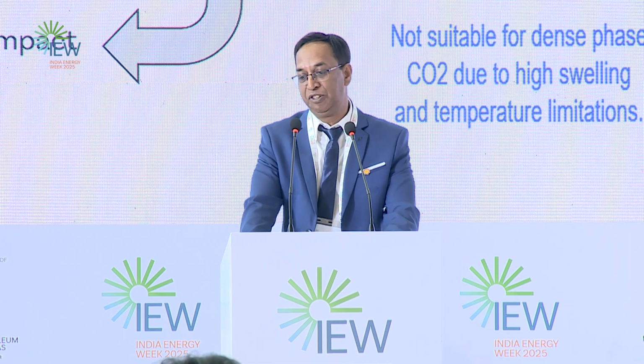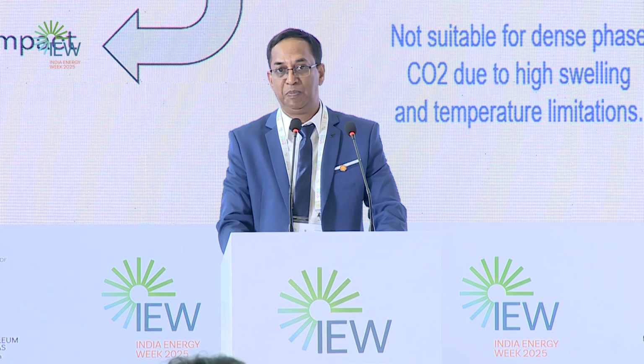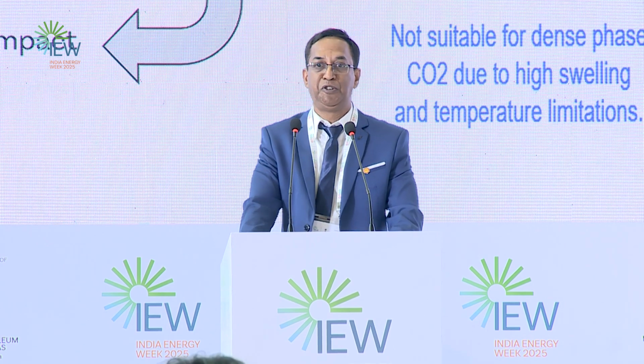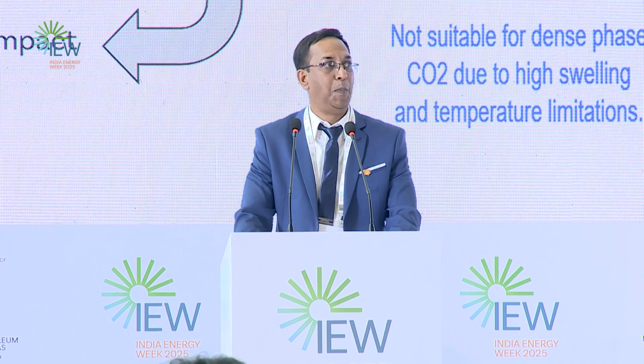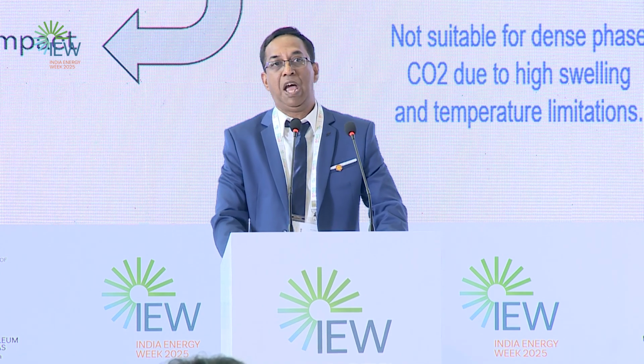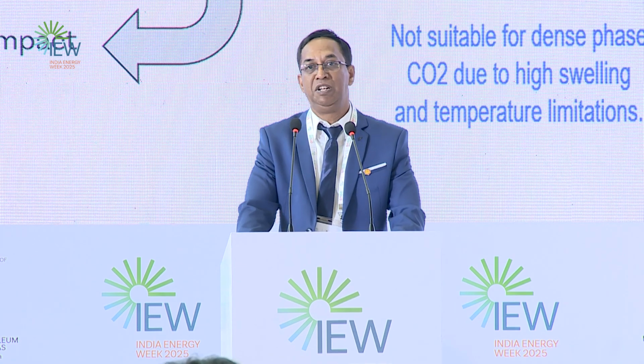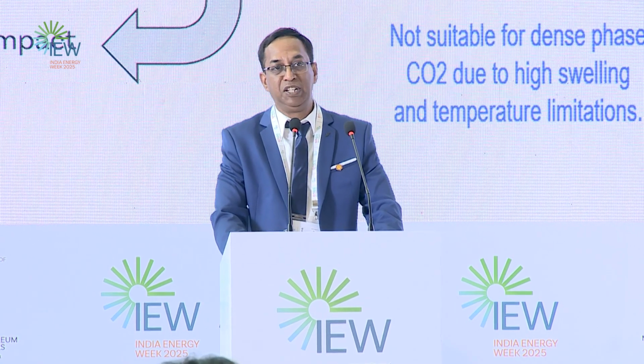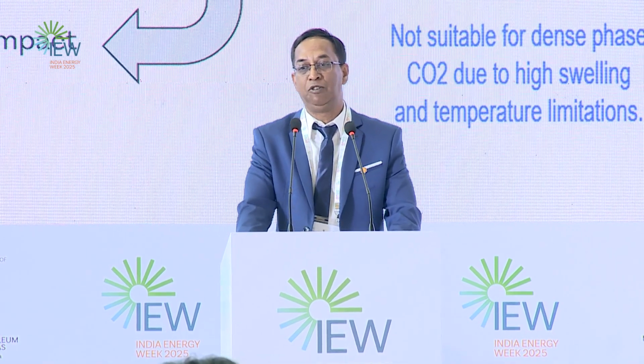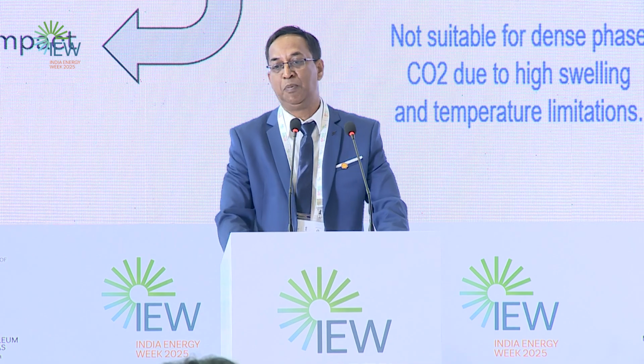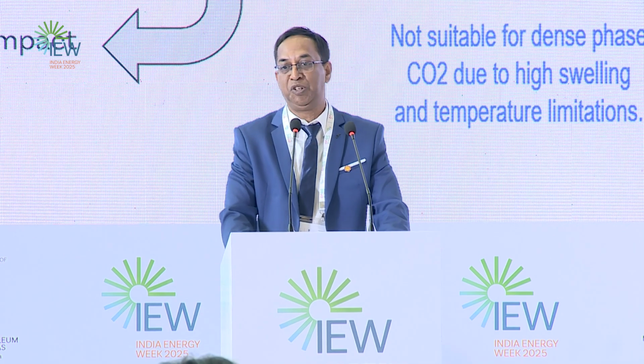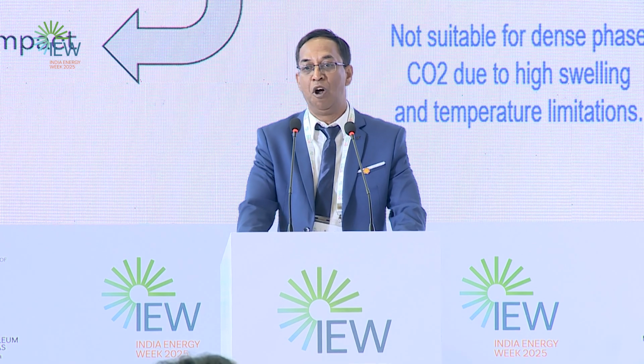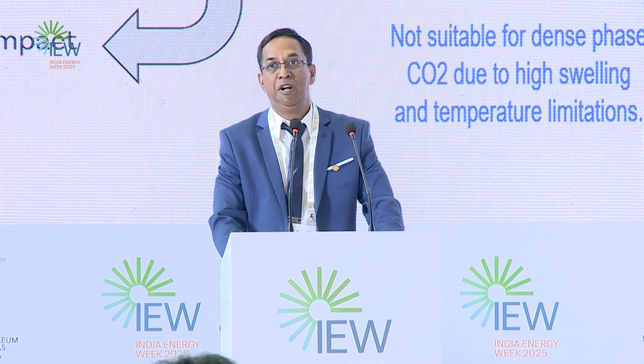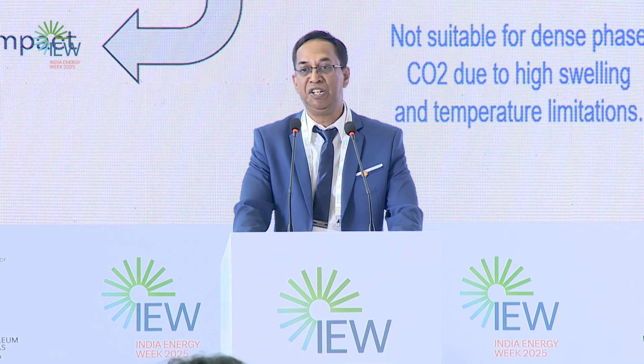So coming back to the design challenges that we have mentioned before, the first and foremost challenge is the material selection. The impurities in the CO2 stream have the potential to combine together and impact the thermodynamic behavior of CO2. And in the worst scenario, it may result in free water formation or corrosion, impacting the integrity of the pipeline. There are alternative materials like CRA or non-metallics, but non-metallics are not recommended because of swelling and rapid decompression issues. CRA is cost prohibitive for a long distance pipeline. So for our pipeline system, we have still gone ahead and used carbon steel for the cost benefit. However, we need to ensure that the CO2 stream is dehydrated, and in our case, the water content is less than 50 ppmv.